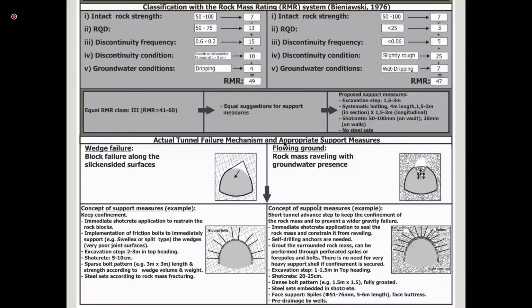But the actual tunnel failure mechanism and appropriate support measures are totally different. So on the left side, we will have wedge failure and block failure along the slickensided surfaces. And this will probably happen very fast because you have a low friction along that. So you're thinking about a specific kind of support, your anchors, like swellex or split sets, in order to immediately support and confine these blocks that you can analyze in your tunnel design.